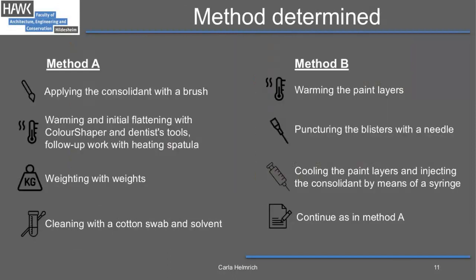For blisters that have stomata on the top or gaps on the surface, method A can be used. Applying the consolidant with a brush. Through the gap, the agent can reach all layers and an even wetting takes place. After about a 12-hour evaporation period, the area is heated with an infrared lamp. At temperatures of around 80 degrees, the paint becomes flexible and can be flattened with a color shaper and dentist's tool. Follow-up work can be done with a heating spatula. Then, weights are placed on the flattened area and left to cool. The surface cleaning afterwards will be done with a cotton swab and solvent.